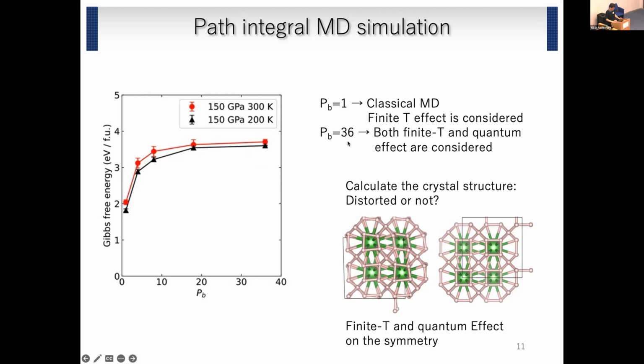In this calculation, both finite temperature and quantum effects are considered. From the MD simulation, we look at the crystal structure for a given pressure and temperature. These are typical examples. In this case, it is symmetric, so no distortion. But when the temperature is not high or the pressure is not high, then the cage is distorted. By looking at this structure and calculating the X-ray diffraction pattern, we discuss the symmetry of the system.